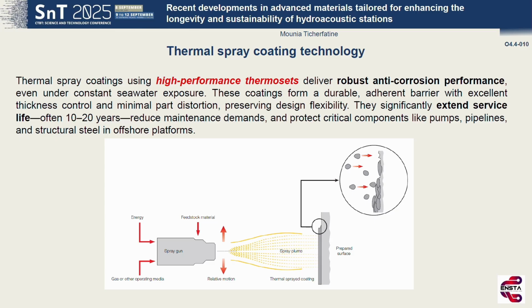Here we have the thermal spray coating, which uses high-performance thermosets to deliver robust anti-corrosion performance, even under constant seawater exposure. These coatings form a durable, adherent barrier with excellent thickness control and minimal part distortion, preserving design flexibility. They significantly extend service life, often from 10 to 20 years. It then reduces maintenance demand and protects critical components like pipelines, structural steels, and offshore platforms.